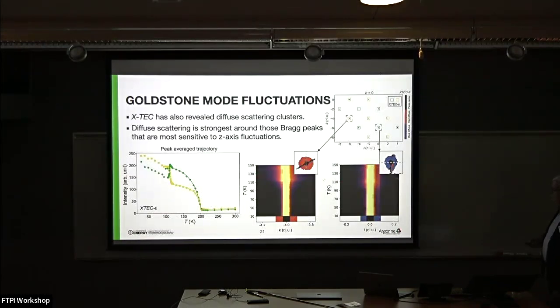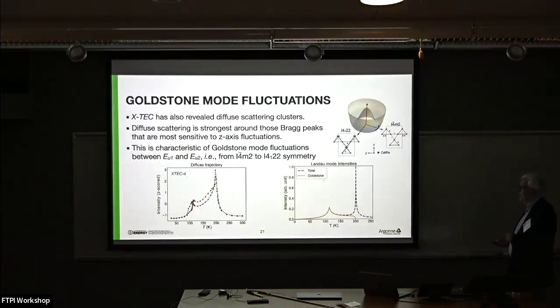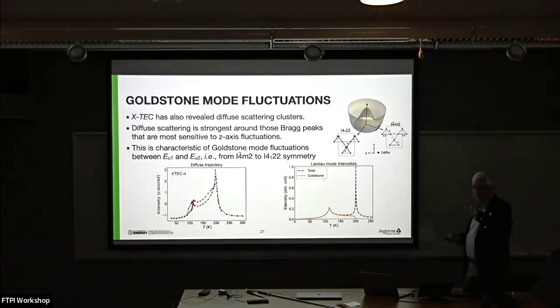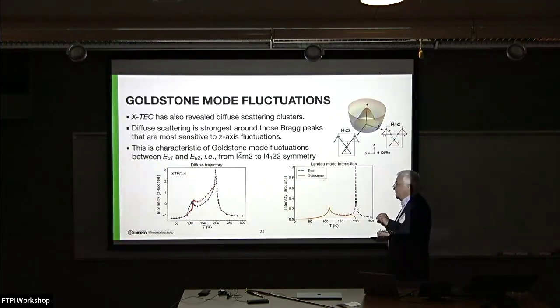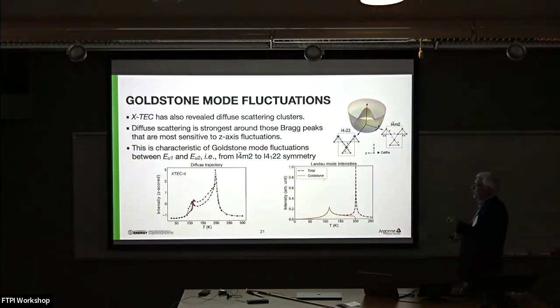Now, if you take the peaks, these yellow peaks are ones which are very sensitive to the z-axis distortion of the cadmium rhenium ions, and the green are sensitive to the in-plane. And if you look at the fluctuations, they're reversed. In other words, you get stronger fluctuations around the ones which have the z-axis fluctuation than the ones which have in-plane fluctuations. And so you can characterize this.